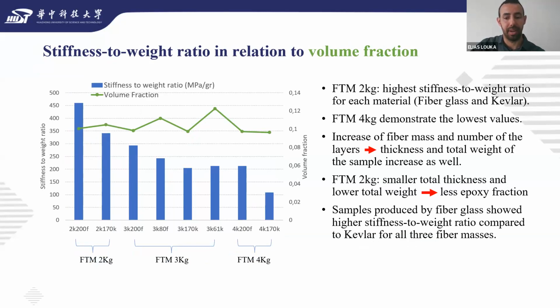Samples with fiber mass 2 kilo have smaller total thickness and lower total weight compared to the rest of the samples, and due to this, less epoxy fraction. Samples produced by fiberglass showed a higher stiffness to weight ratio compared to Kevlar for all three fiber masses. Let's move to the final result of this research.